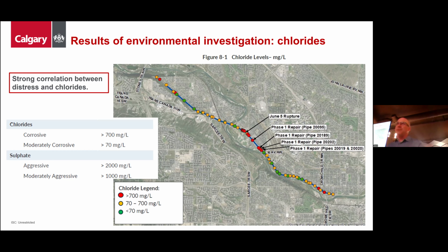So I can tell you specifically a story that I had heard from one of our soil testers in and around this break location, one of the 5 hotspots here. The testing back in 2014 was in the order of 700 milligrams per liter for chlorides. When we tested it last year, it was 8,000 milligrams per liter, which is, as the soil sampler put it himself, "I thought I put my sampling tool in a bucket of salt." It's actually that high of chloride. So it's actually significant chlorides, really quite significant. Something that took us totally off guard.